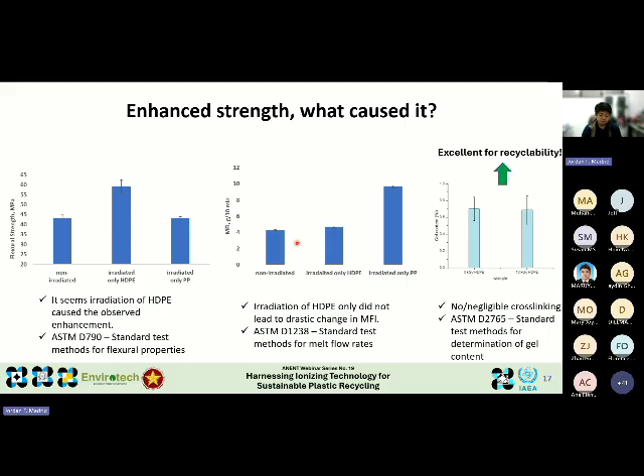And so we made further studies, further tests for the irradiation of HDPE, and we asked ourselves whether the HDPE cross-links during irradiation. So we measured its gel content. However, we observed that there is minimal to almost no cross-linking.